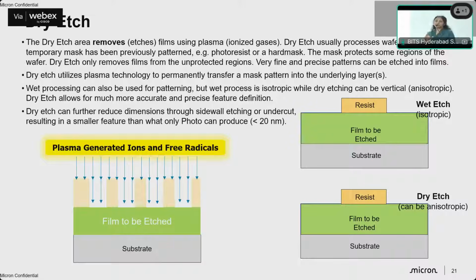Depending on the type of chemical you're using in this dry etch area, that determines what material you are going to remove. So it's not a standard process. If you want to remove, say, an oxide film, it will use different dry etch gases, and if it's a nitride, something else. There are other options also.